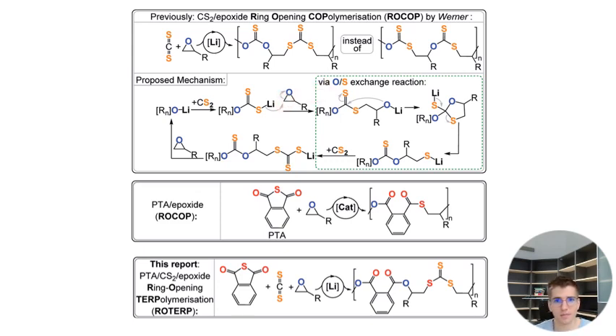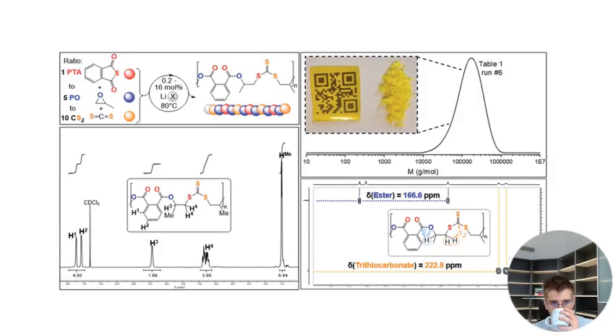Okay, so let's go. How did this look? Sorry. So I took the monomer combination at the 1:5:10 ratio. This would go into hundreds and thousands of equivalents with respect to lithium, so as low as 0.2 mole% of the lithium alkoxide. And here you could either use lithium alkoxides or lithium HMDS. Both worked. So both alkoxides and HMDS initiated the polymerization. To form the structure, I remember mixing it, and then you got a viscous mixture that is soluble in dichloromethane, and you can precipitate it in methanol, and then the NMR spectrum of the polymer looked like this.